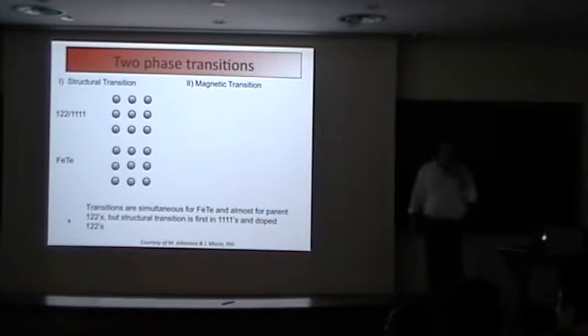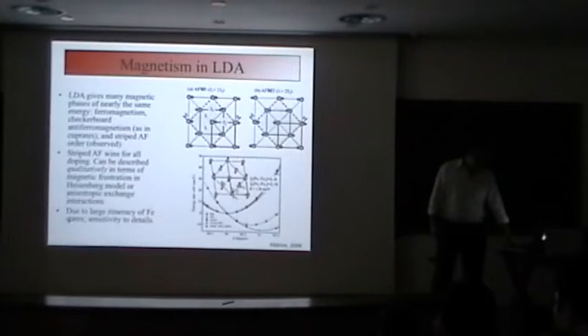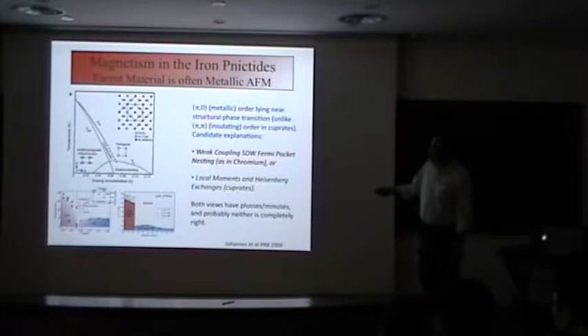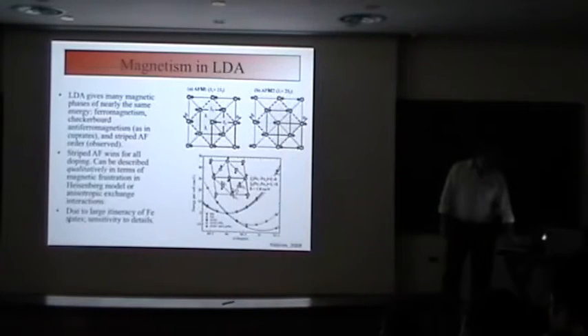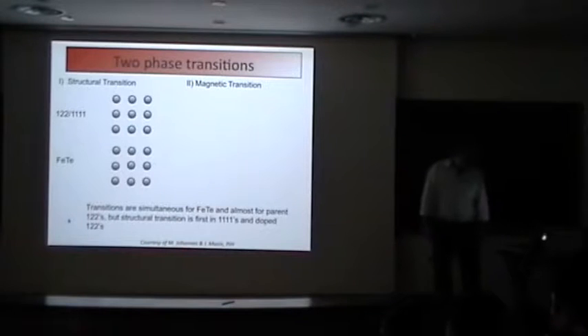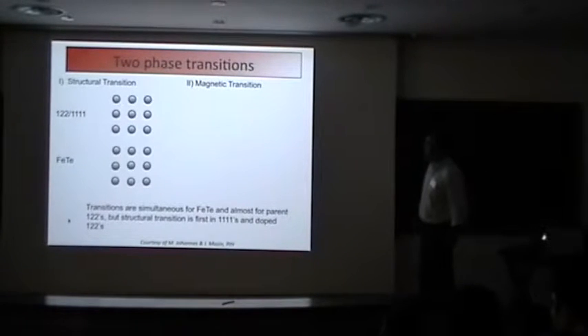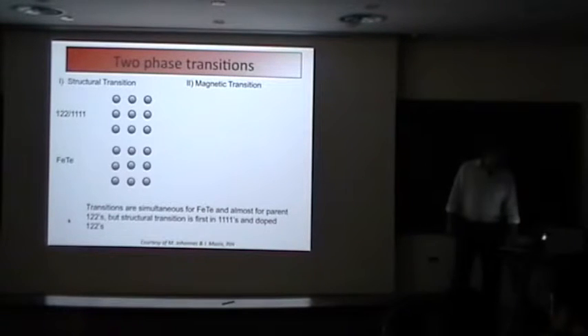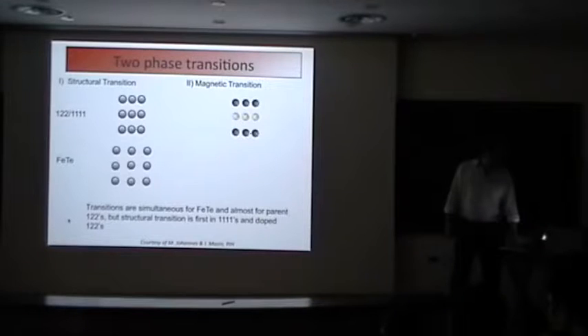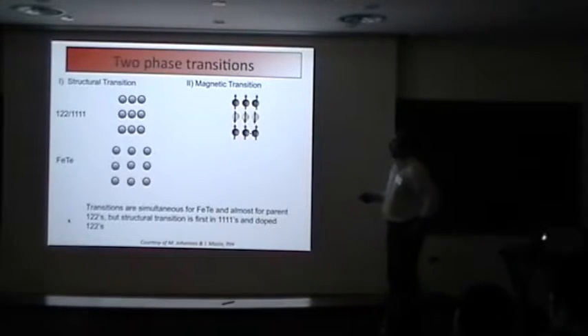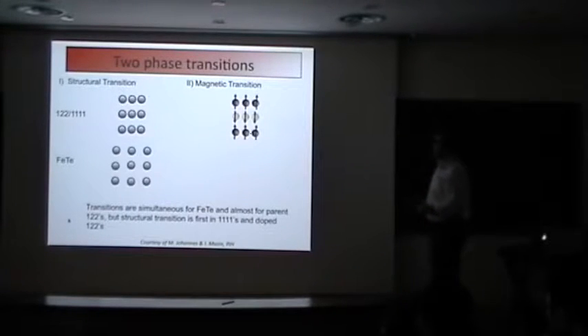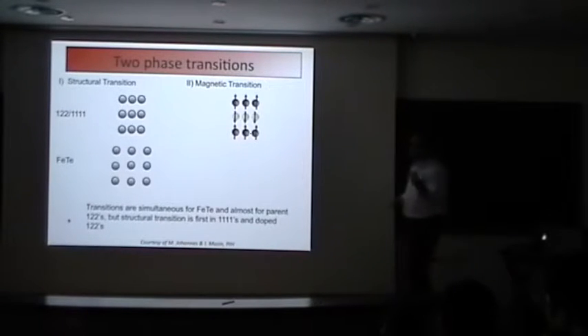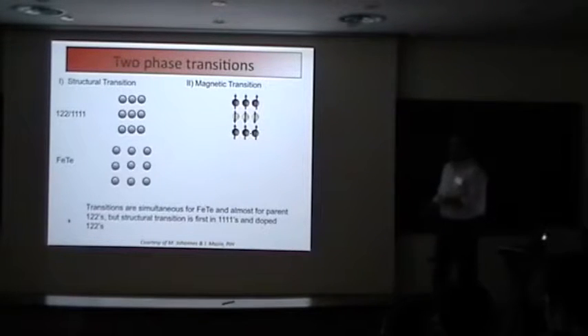Another is to look at the connection between the structural transition. Go back - this line here is very different than in the cuprates. This thing just seems to hug the antiferromagnetic phase boundary. So LDA has also weighed in on that, understanding things from the structural point of view. This is a slide I stole from Peter, but one could understand that the structural transition of making things orthorhombic in the 122 and 1111 compounds might prefer a particular orientation for the magnetism, connected to the physics of crystal field exchange, Hund's rule, plus delocalization.